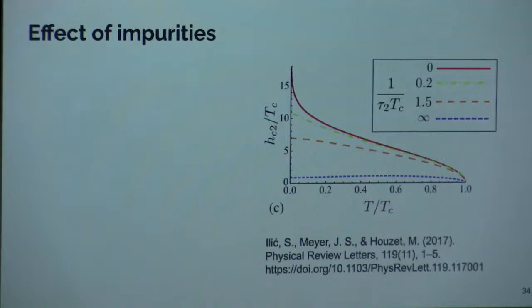So if we apply a simple superconducting theory to monolayer TMDs with spin and momentum degrees of freedom, then this theory predicts that on-site impurities actually suppress the critical field. The reason for that is that on-site impurities counteract the Ising spin-orbit coupling, in this way destroying superconductivity.